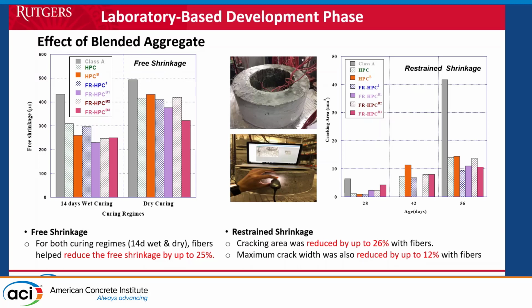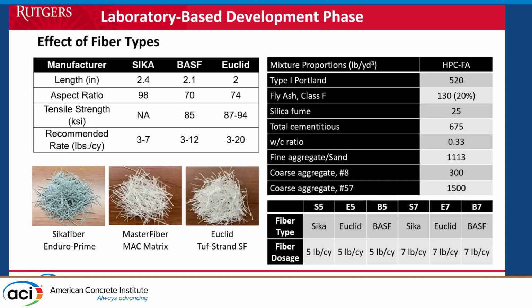We also used the restrained ring under restrained conditions, and we monitored in the lab which mix had the best potential for minimizing the cracking density and the cracking area. We did that on all the mixes, with both wet curing and dry curing, meaning air dry. This is one of the conditions because the contractors were complaining that 14 days of wet curing adds a little bit more cost to them.